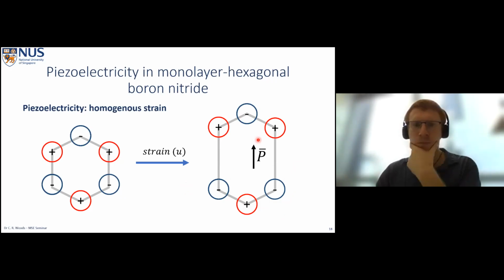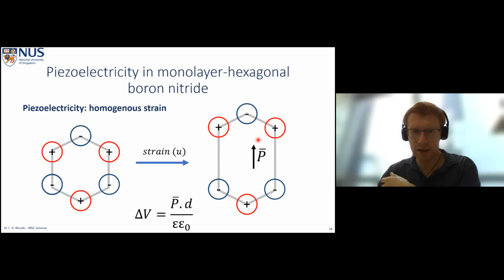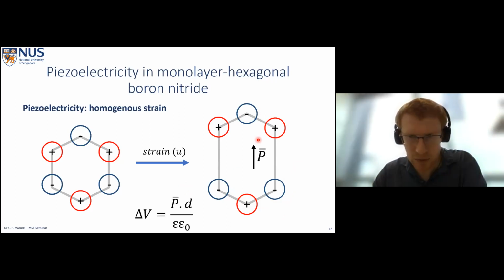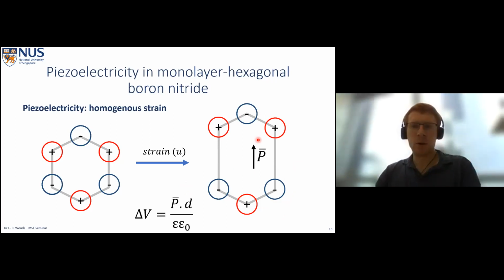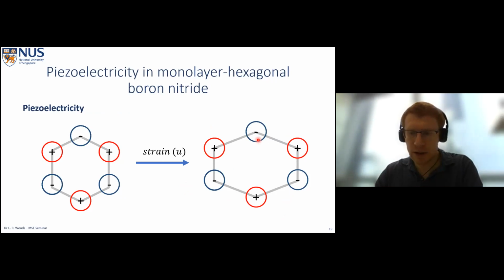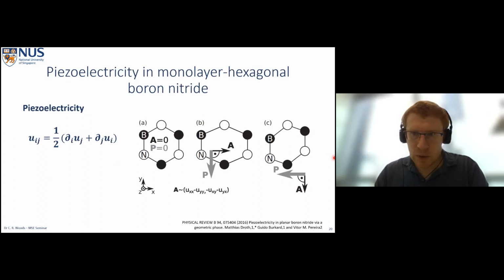inhomogeneously. And this polarization field will just give us a potential difference from one side to the other, given by the distance over which we have this polarization. We can also strain our sample in the other direction. And if we do this, then we get a polarization which points in the opposite direction. So depending on which axis we use to strain the crystal, we can change the direction of our polarization. And actually, if we begin to add in some shear strain as well, then we can get polarizations in all directions.